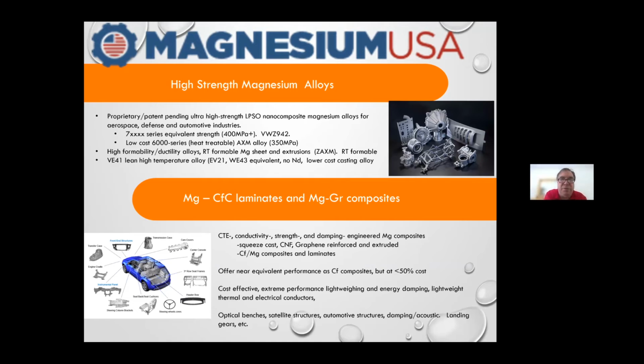lightweighting. And these include very high temperature, high strength, long period stacking order nanocomposite alloys that are 6,000 and 7,000 series equivalent, up to 500 megapascal materials, and some low cost 6,000 series heat treatable materials that are very low cost alloys. We also have some high formability ductility alloys, room temperature formable extrusions, and eventually sheet, and a lean high temperature alloy that is for high temperature casting applications, that has no neodymium and is more friendly on the rare earths and lower cost than traditional EV21 and WE43 materials.